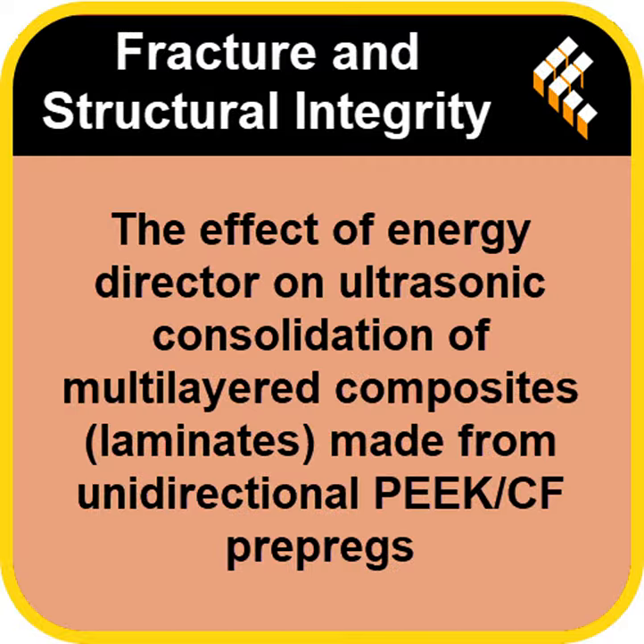Wow. And the analysis showed something really bizarre, didn't it? The prepreg layers themselves. They actually got thicker. They did. For the ED samples, the prepreg thicknesses actually increased as the time went on. That's the smoking gun right there. It is. It's the visual proof that the molten polymer from the ED was being pumped or forced into the prepreg layers. Instead of making a nice clean bond on the surface, it was pushing the structural layers apart from the inside, causing internal damage and weakening the whole thing.